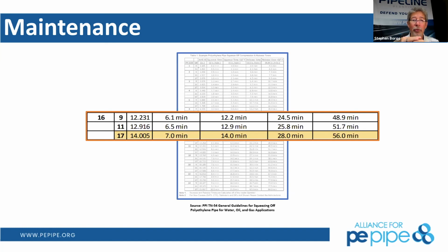And so the first two columns here, you have the size of pipe. You have your size, you have DR starting on the left-hand side, DR 9, 11, and 17. And you have the ID. I believe that's the ID of the pipe. Yep, thanks, Matt. And then you have the squeeze times at different temperatures. If it's cold out, you have to do everything slower. So above 32 degrees, DR 17, 16-inch would be 7 minutes to squeeze the pipe. If it's below 32 degrees, then you have to take 14 minutes to do that squeeze.